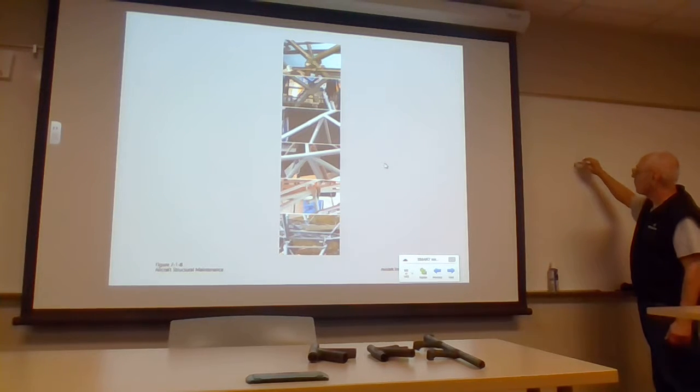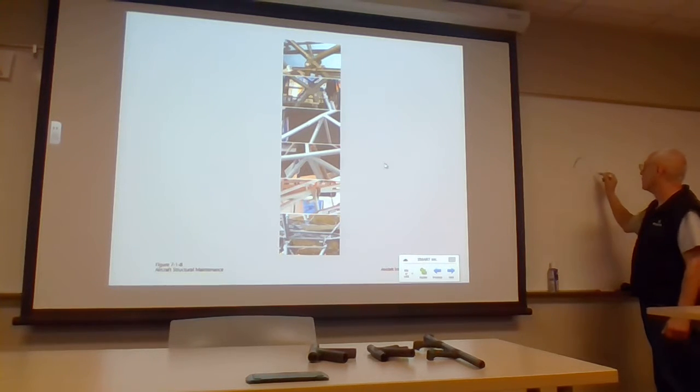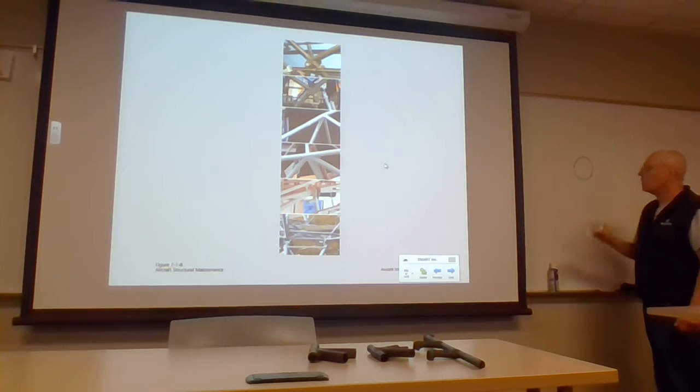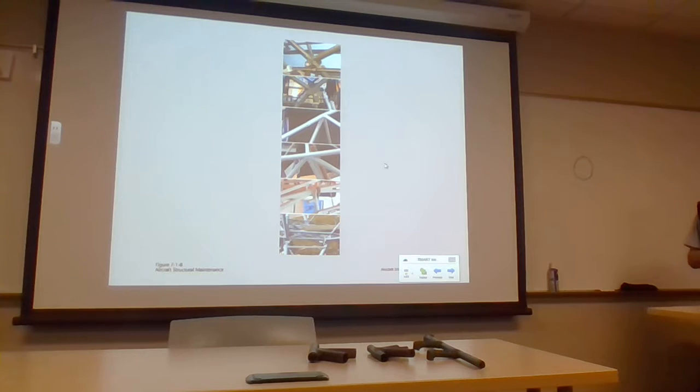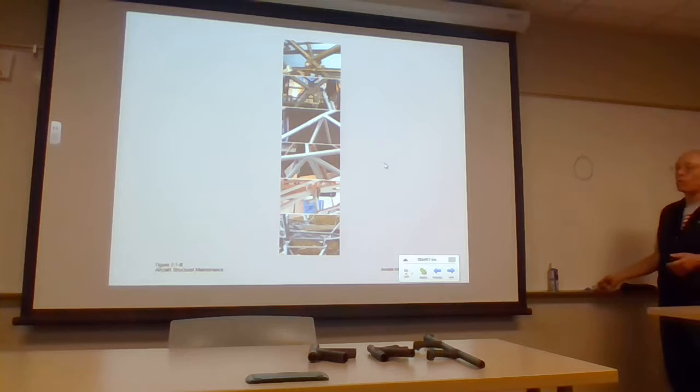So they might have a weld that kind of begins over here, and then they'll weld maybe a quadrant over here, and then they'll come back over here and weld this quadrant, and they'll come over here and finish it off over here. What that does is it spreads the stress out somewhat evenly so that the tubing doesn't end up bowed. So they call that technique quarter welding, and it's commonly done with a lot of tubing anyway.